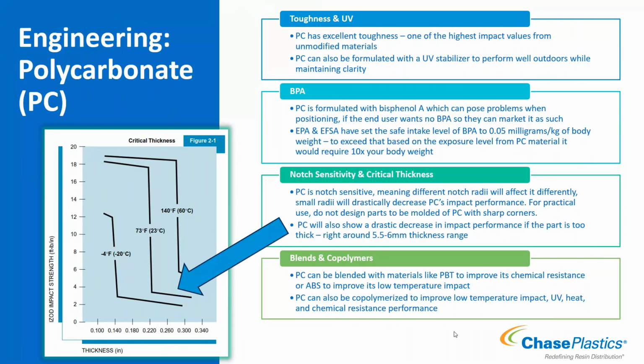Polycarbonate has excellent toughness, great impact performance when we talk about unmodified materials - 10 plus foot-pounds per inch IZOD out of a standard polycarbonate, as long as we're not getting too small of a radius or too thick of a part. Polycarbonate can also be formulated to utilize a UV stabilizer and maintain clarity. A lot of times when you start adding stuff to clear materials, you start losing the clarity because you have something else competing with allowing the light through, but polycarbonate can be formulated with UV stabilizers and maintain its clarity.